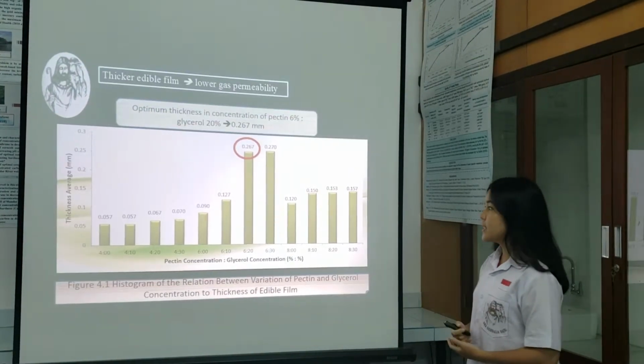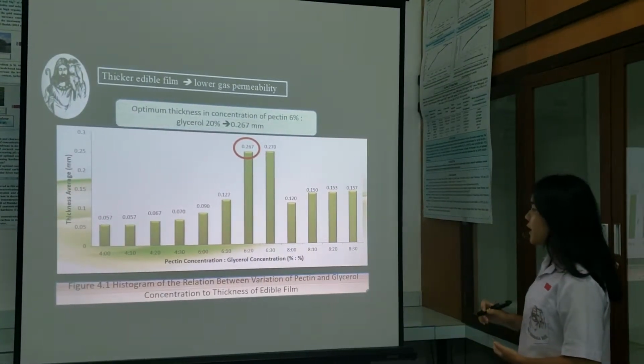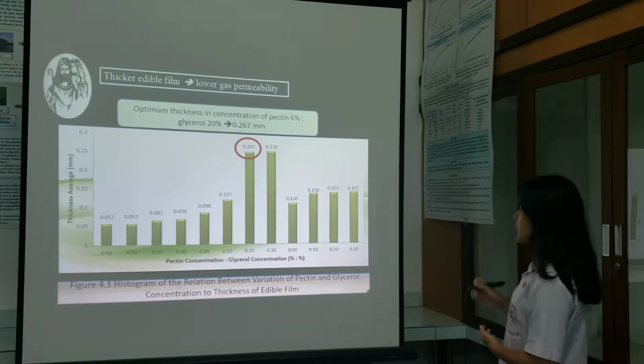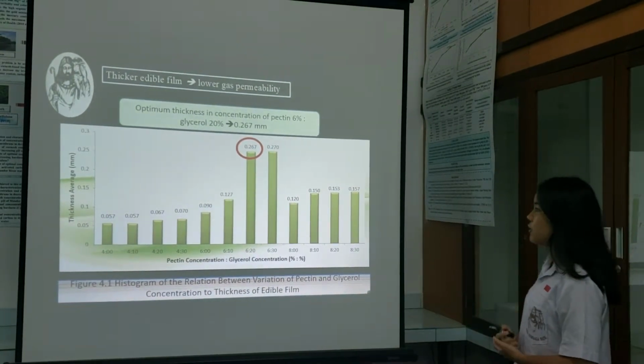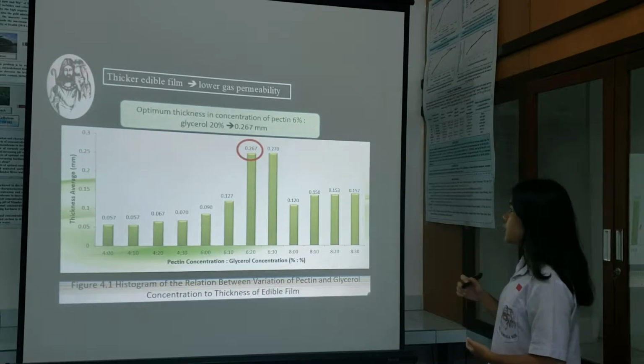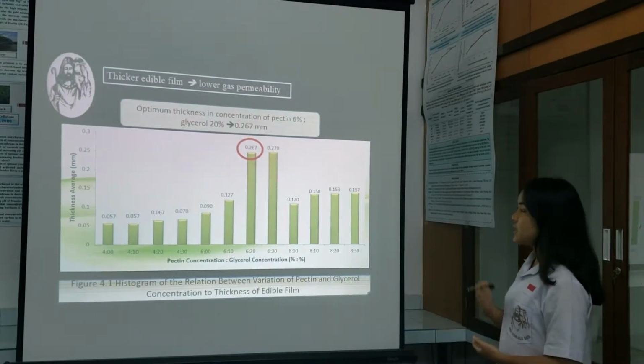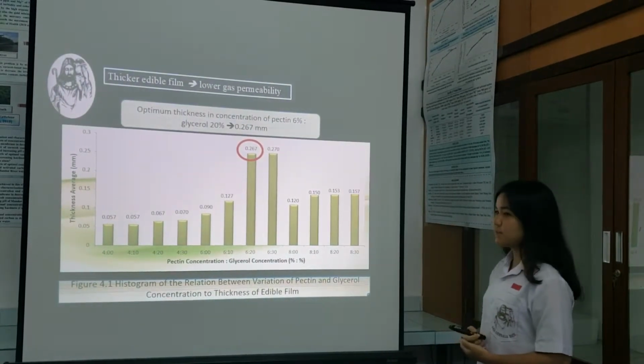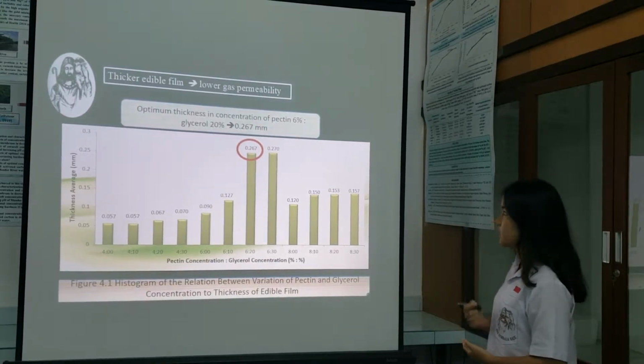My honorable judges, as we can see on this following graph, the optimal edible film variation is 6% pectin, 20% glycerol with the thickness of 0.267 mm. Thicker edible film will result in lower gas permeability and can protect the packaged product better.